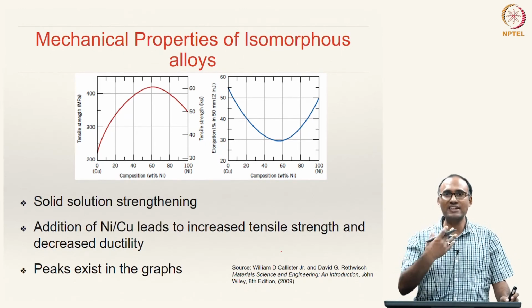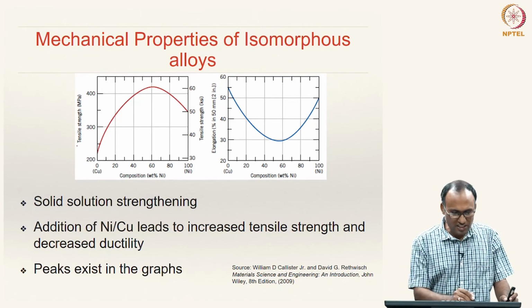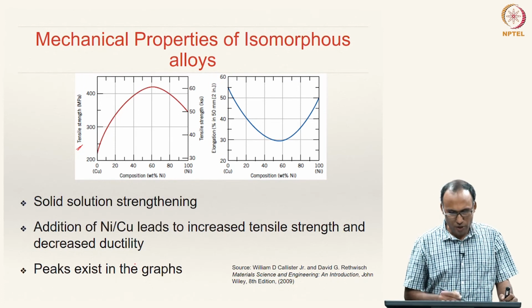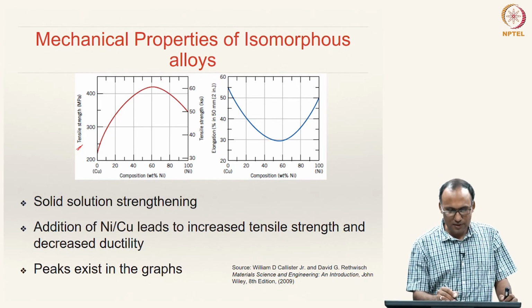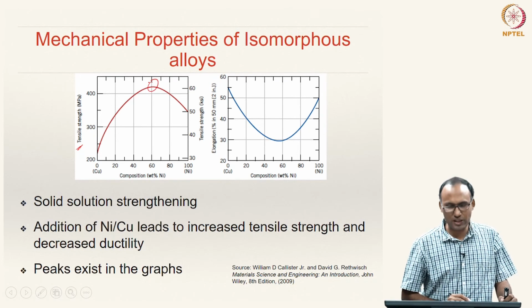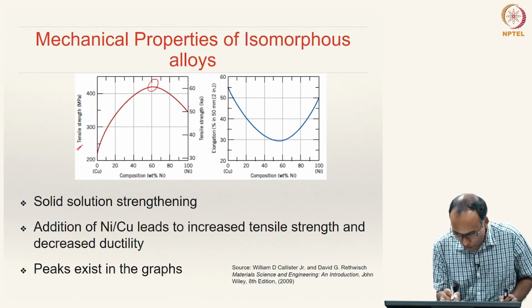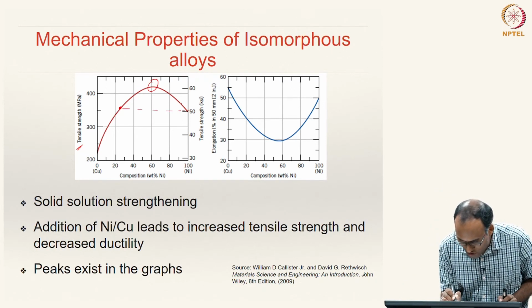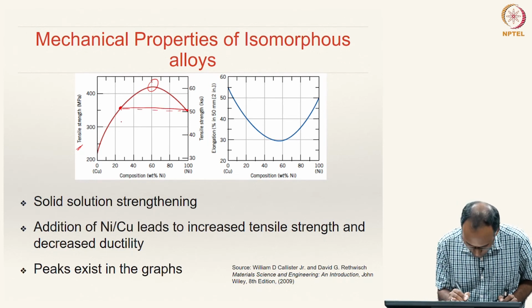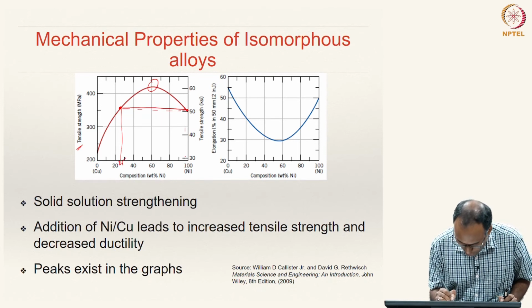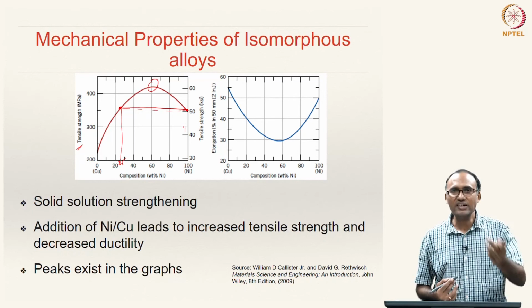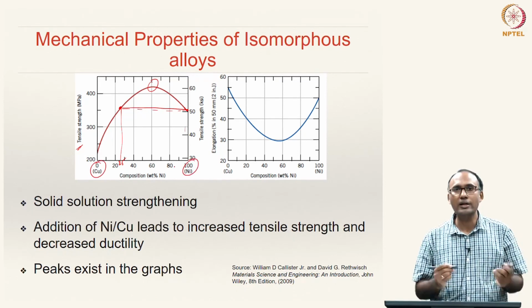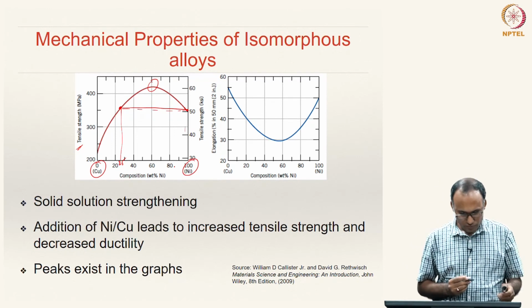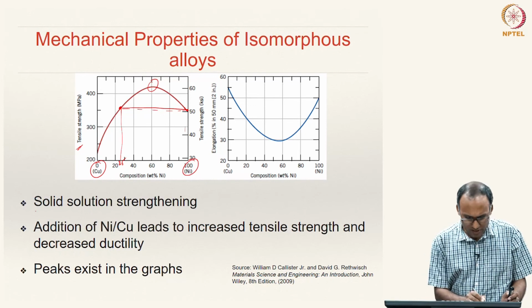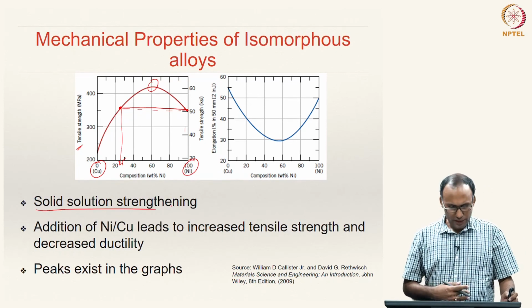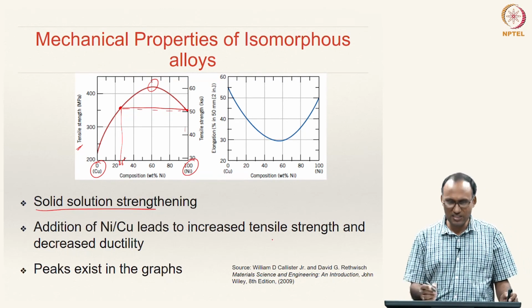Okay. So, now let us look at the mechanical properties, why are we doing alloying, as we have discussed we can enhance the mechanical properties, right. So, if you look at the tensile strength of copper nickel system, you can see that the tensile strength of these alloys, particularly if you take about 60% nickel one, has the maximum tensile strength. So, all the alloys from this composition to this composition, from say 25 to almost 90 are going to give you a higher tensile strength than both copper and nickel independently, right. So, this specific strengthening mechanism is called solid solution strengthening. So, addition of nickel and copper leads to increase in tensile strength and decrease in ductility.